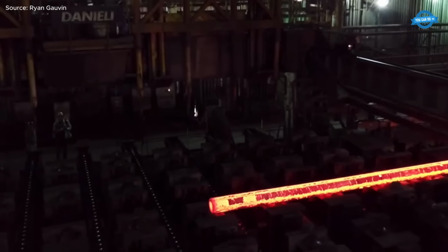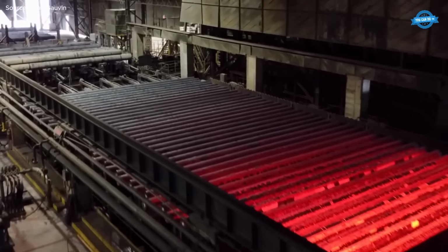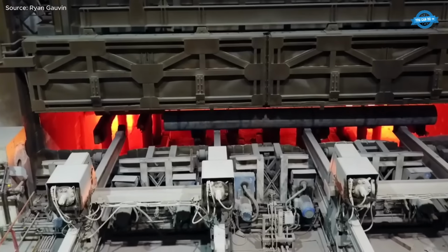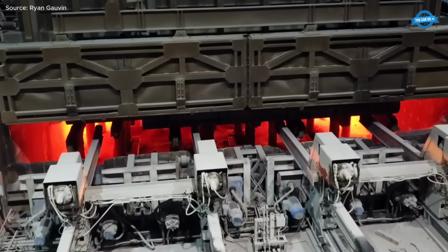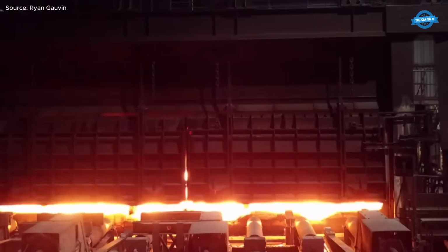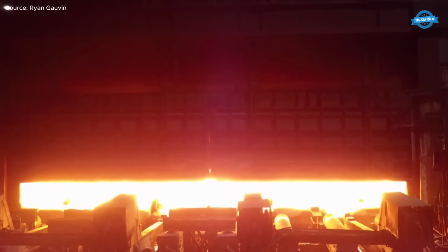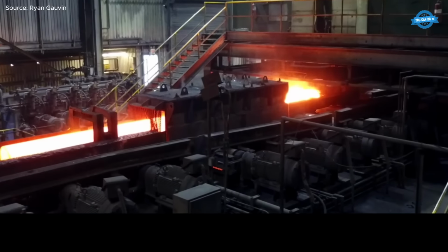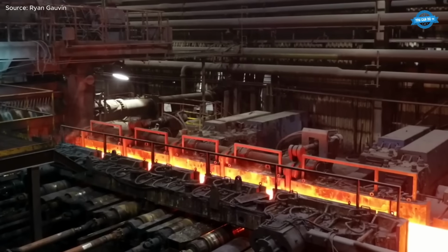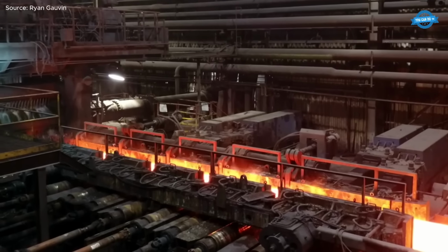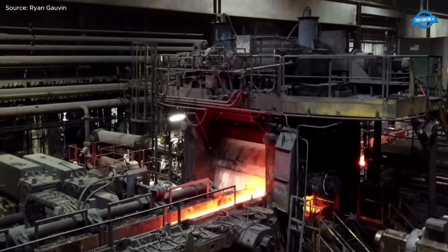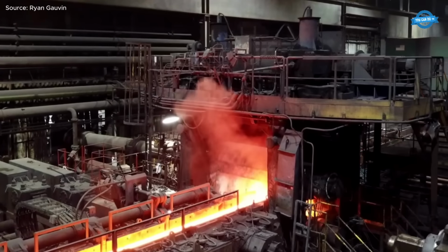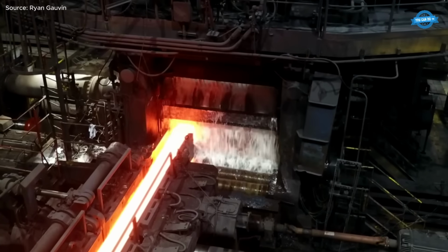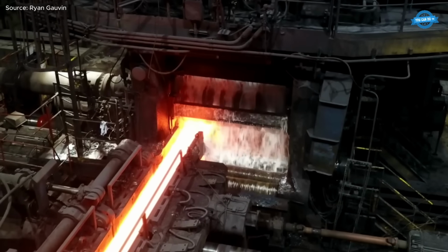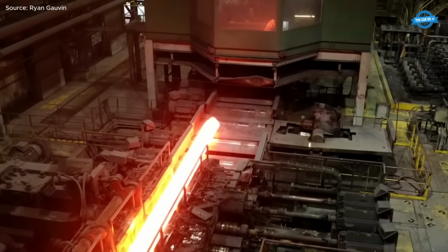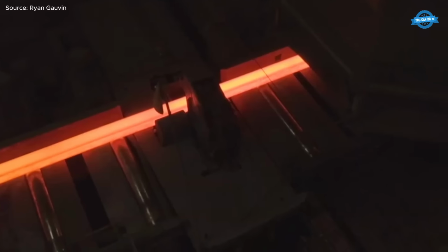Once cut and cooled, blooms are charged into the rolling mill reheat furnace. After reheating, high-pressure descaling removes surface scale before the reversing breakdown mill reduces the section. Cropping trims the front end, and inline rolling progressively shapes the bar. Final operations include controlled cooling, shot blasting, chamfering, dimensional verification, and inline non-destructive testing to ensure mechanical integrity and surface quality.